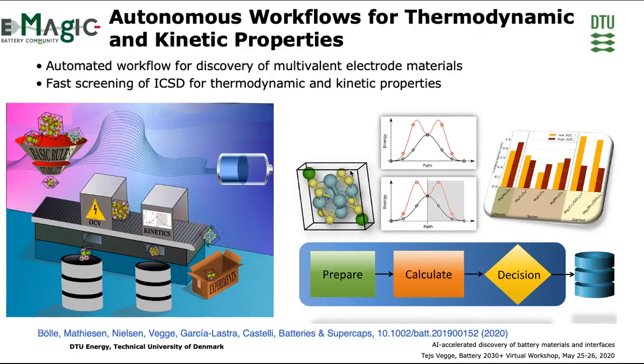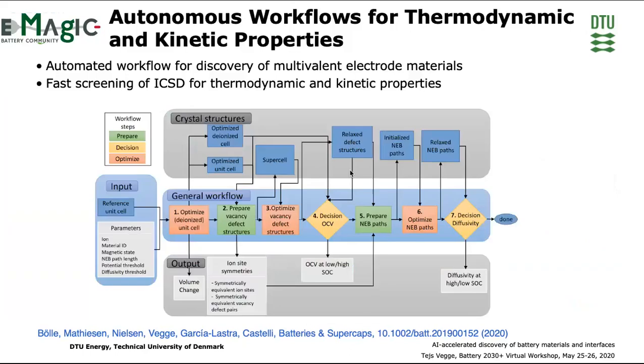So this is work by Felix Bølle and Ivano Castelli that you'll hear from later on today, on using an autonomous workflow that takes materials from the ICSD, analyzes not only the thermodynamic properties, but also the kinetic properties in an automated fashion to select suitable materials for synthesis and characterization. So what Felix did is really to generate this autonomous workflow that selects materials from the ICSD based on certain structural properties, sets up calculations automatically that allow us to assess thermodynamic properties at both high and low state of charge, but also to calculate the kinetics. Those of you doing calculations know that kinetics are typically very difficult to get. So it only does the level of calculations that are needed.